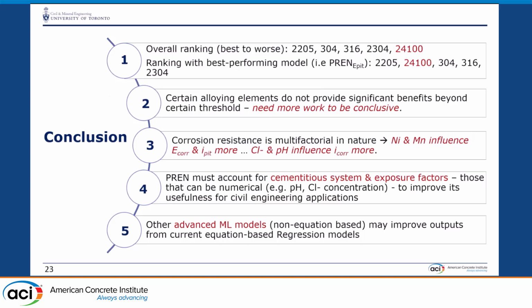In conclusion, the overall ranking based on the commercial grades of stainless steel is that duplex 2205 ranks first, the molybdenum-free 304 ranks second, and then 24-100. One thing we find about the 24-100 is that it's completely manganese based with no nickel, so there needs to be some nickel balance to improve its corrosion resistance. It's very sensitive to E-pit, so the position changes depending on what you're looking at. Certain alloying elements do not show beneficial effect beyond some threshold.